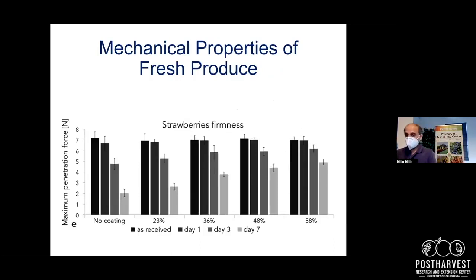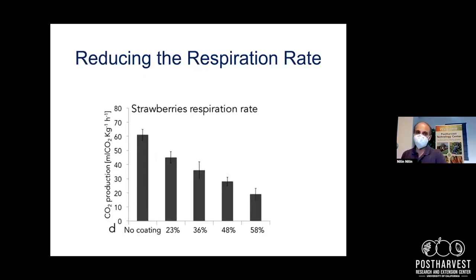It was remarkable what they showed in terms of the firmness of the fruit. As you can see, without the coating, they lost a significant amount of the freshness or firmness of the fruit. And with coating, they were able to retain most of it even past a week or so of storage. So these are some of the features that we look for when we think about the functional product and its interaction with the produce in this case.